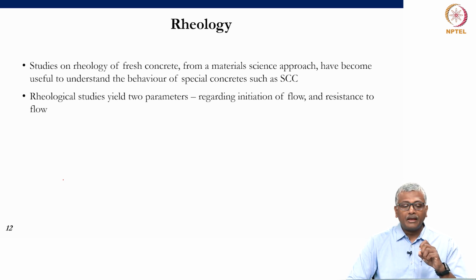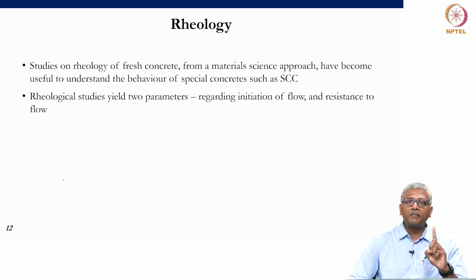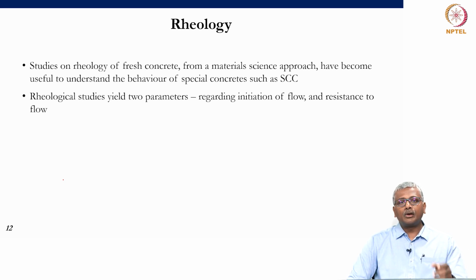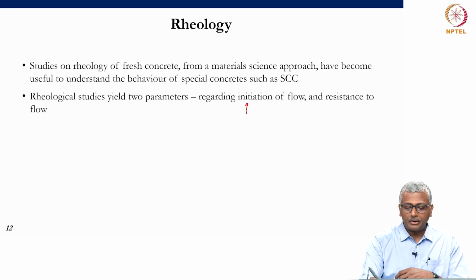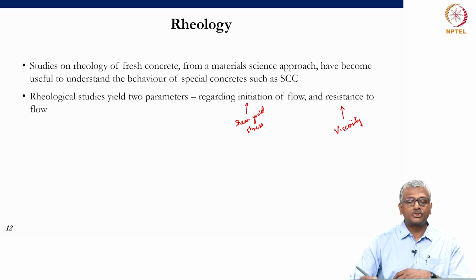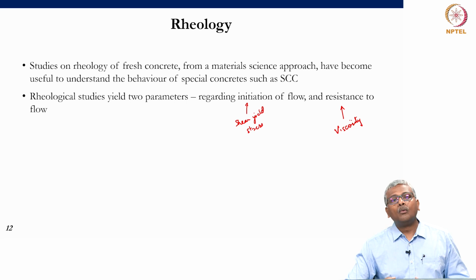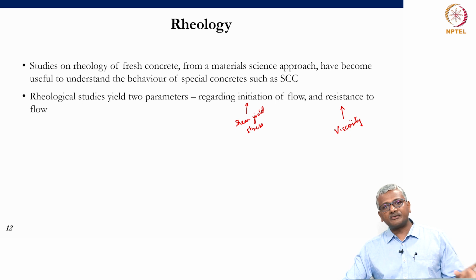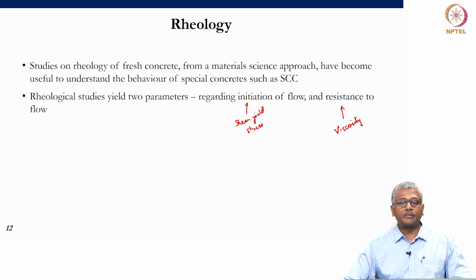Okay. So instead of workability, which gives only one parameter like a slump or a compaction factor, rheological studies will tend to give you two parameters. One is called shear yield stress, which talks about the initiation of flow, and the other is viscosity, which relates to the resistance to flow. Once the material starts flowing, what is the resistance to the flowability? And that is determined by the viscosity of the material. So, shear yield stress and viscosity typically are achieved using rheological measurements. So, let us see what these physically also mean.